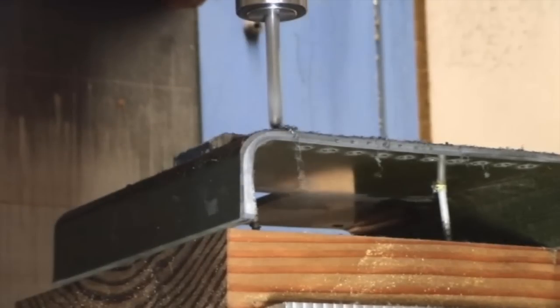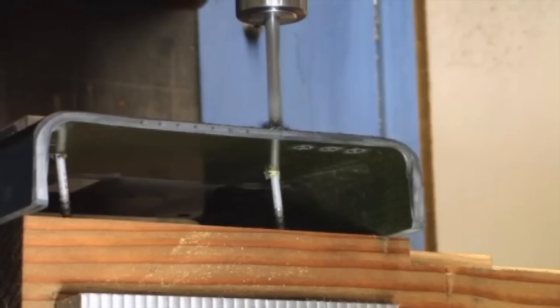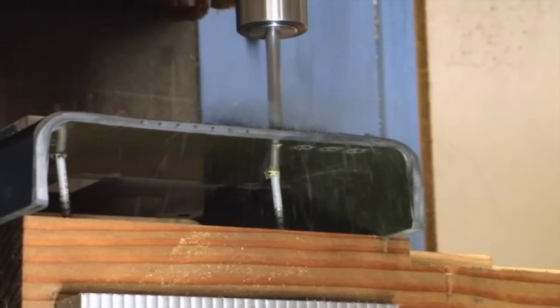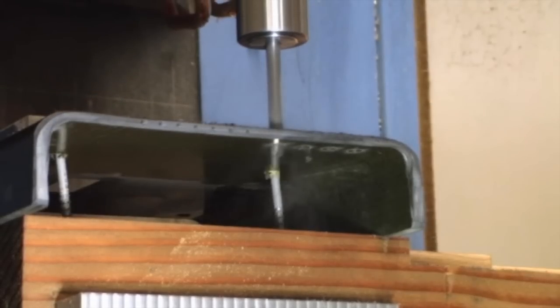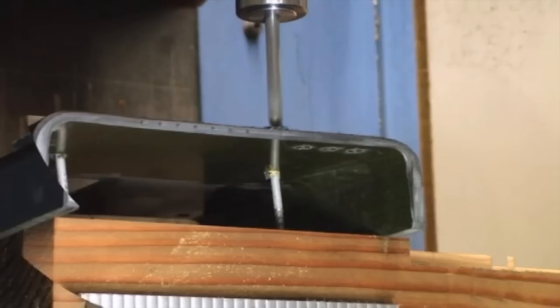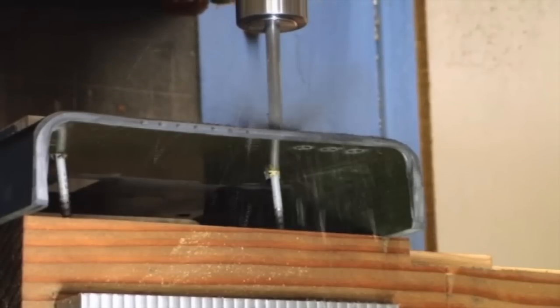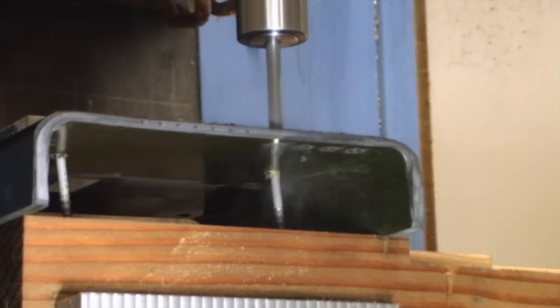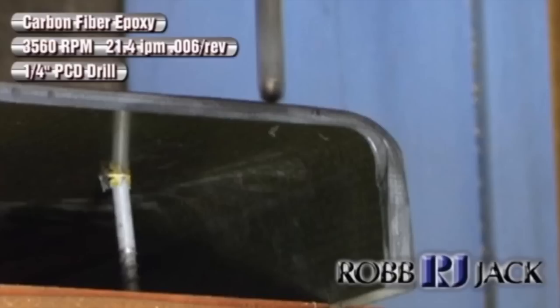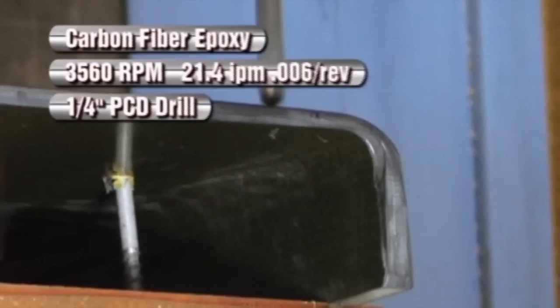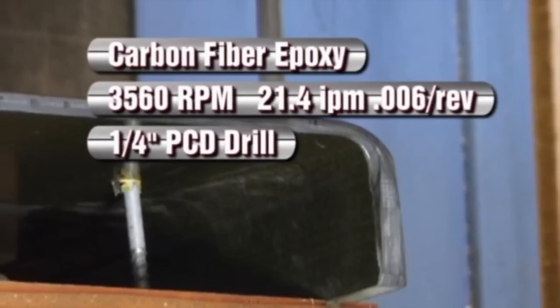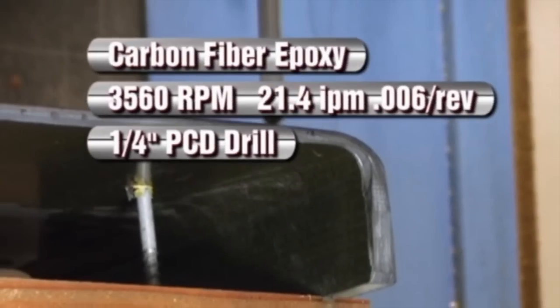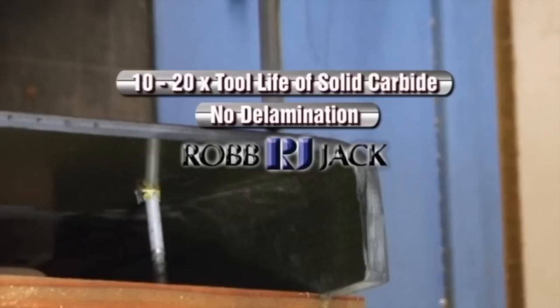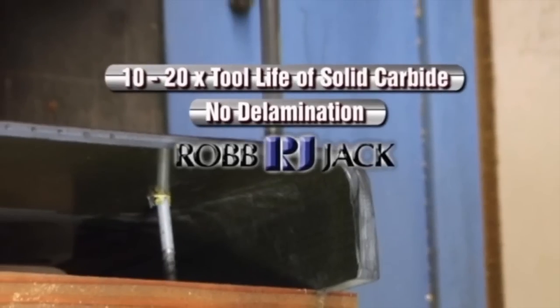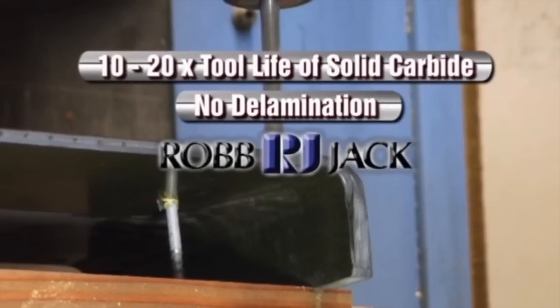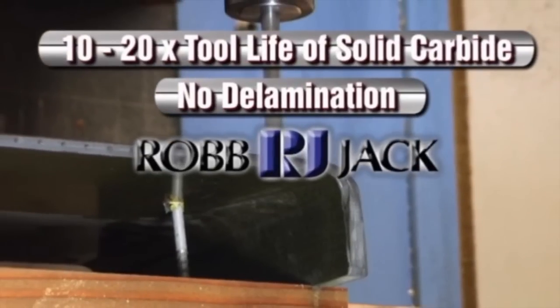So as soon as you wipe it off and look at the finished part underneath the microscope, there are no uncut fibers or delamination. So by having those really sharp cutting edges, the really clean geometry specified for composite materials, we're able to cut really clean holes with no delamination or uncut fibers. And you can get typically anywhere from 10 to 20 times tool life over solid carbide.